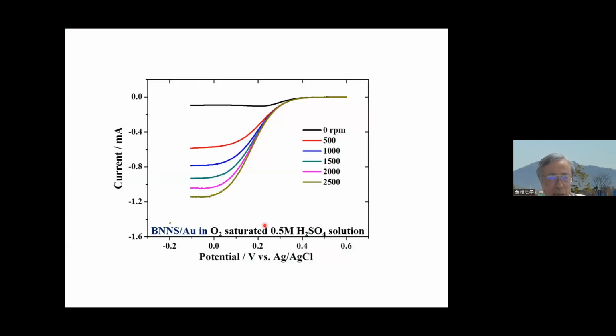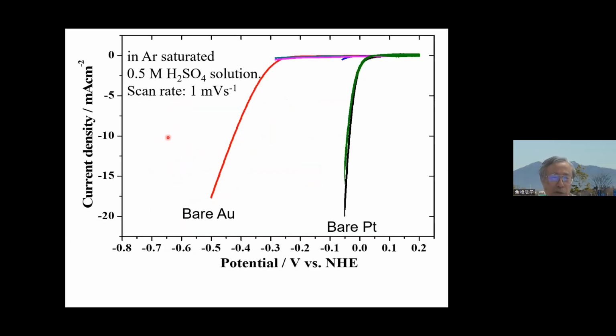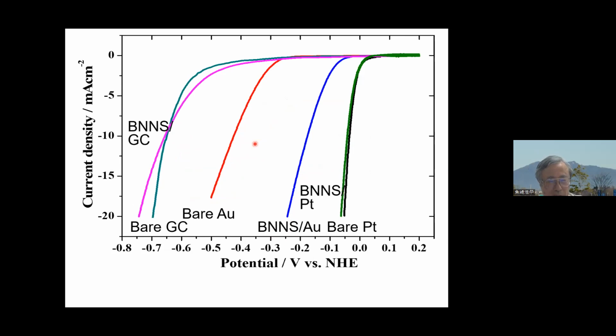Accidentally, we found that this electrode is also effective for hydrogen evolution. This is the oxygen reduction current obtained by rotating the electrode at different rotating rates. Usually we stop here, but at one time, my postdoc applied more negative potential and we saw some current increase. What is this? Maybe hydrogen evolution. This is bare gold and bare platinum. Gold is very bad compared to platinum. But by modifying gold with boron nitride nanosheet, the overpotential decreased quite a lot. So the boron nitride nanosheet gold is very good, but not boron nitride nanosheet on glassy carbon, with no platinum.